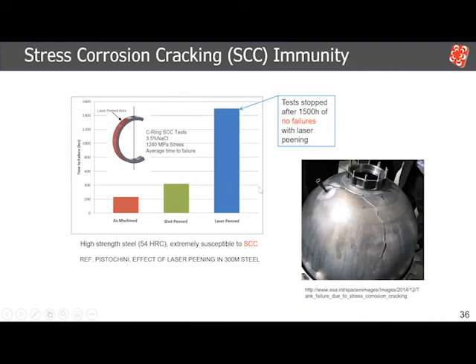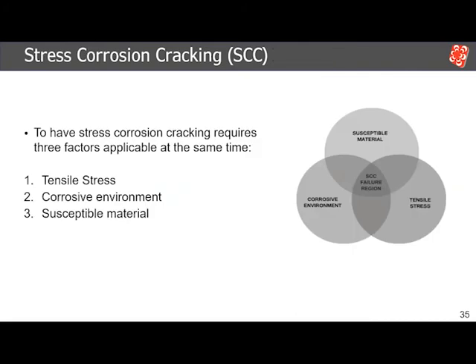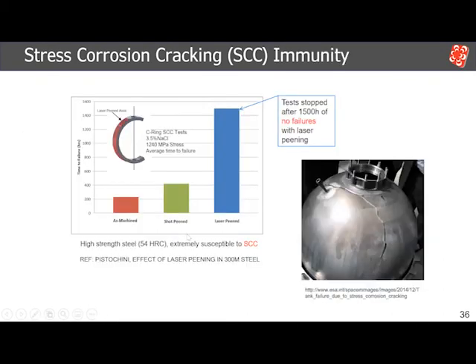So now let's think, how did laser peening get that benefit? So going back to the basics, tensile stresses. Laser peening was able to generate high compressive stresses to a depth that you're protecting the surface and the subsurface, which is the most susceptible areas here in this component. When you're countering these tensile stresses, you're removing one of these three main factors that cause stress corrosion cracking. And that's how laser peening was able to mitigate any failures in this type of testing for stress corrosion cracking.